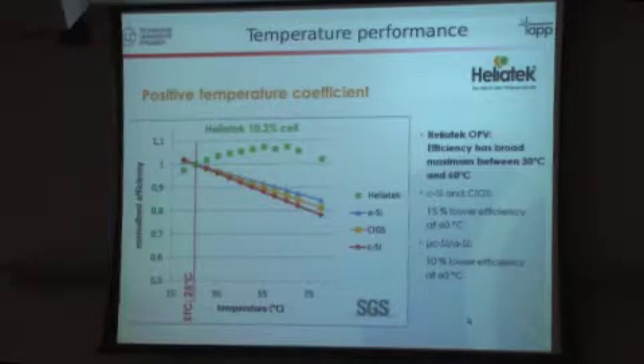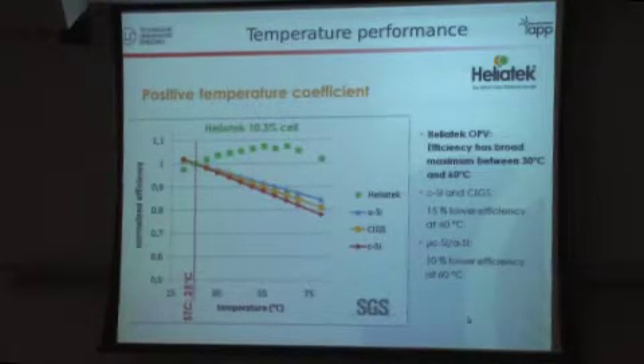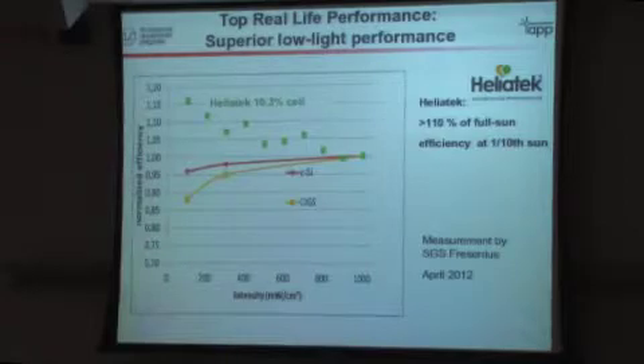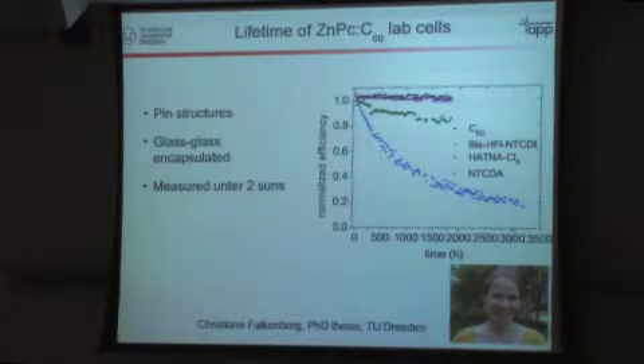To show you part of these data, these are measurements by Heliatek on 10% cells, and as you can see, the organic cell is getting significantly better to the operation temperature, whereas all other PV technologies go down. And same for intensity. If you go down from 1 sun to say 0.2 suns or so, organics go significantly up and all the other technologies go down. And altogether, with an angular effect, you have this nearly 30%. Frankly spoken, however, the better our cells will be, the less this effect will be.